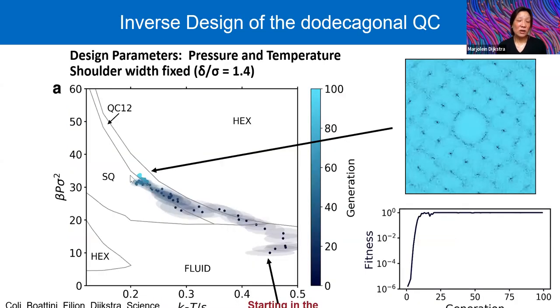So we start from this, and this is the phase diagram in the pressure-temperature plane. We start, for instance, with our Gaussian distribution in the fluid phase. We then draw N samples from this Gaussian distribution, so N combinations of pressure and temperature. We then perform simulations for these N pressure-temperature combinations. And then we calculate the diffraction pattern, and we use the convolutional neural network to tell us what the probability is that it belongs to a quasicrystal. And then we move the Gaussian distribution in a way that it goes to the higher probability that it belongs to the quasicrystals.